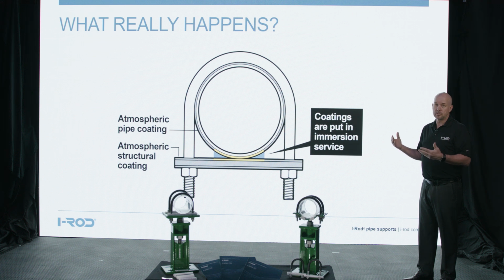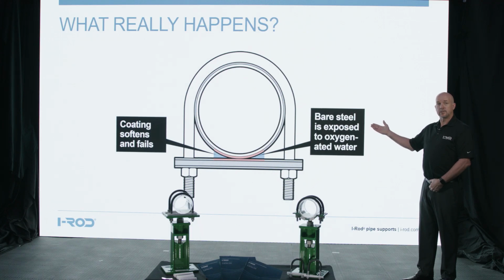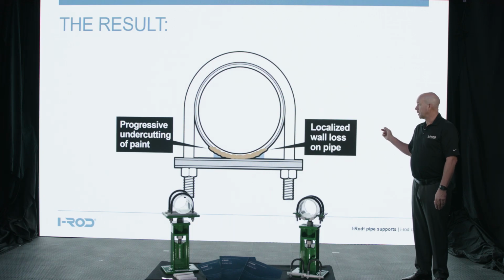The problem with that is that the coating on the pipe and the coating on the support is an atmospheric coating, which means that it's meant to be out in the atmosphere or dry most of the time. But here at the bottom where this crevice is and where water is trapped, the coating is in contact with water all the time, which is similar to being put in an immersion service. Eventually, the coating begins to soften and separate from the steel, and then you have bare steel in contact with the oxygenated water. Once the coating is separated from the steel, you start to see progressive undercutting of the paint. And then you see localized wall loss, which becomes a real problem.